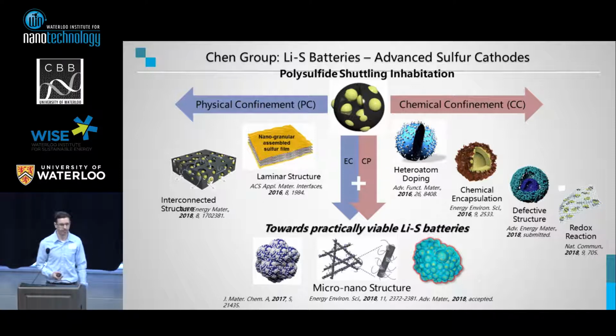But there are similar life cycle considerations for that as well. So right now, this technology is only very early beginning to be introduced into the market, and there's still much more improvements to be made. So the main consideration here in terms of chemistry is that sulfur, when it joins with lithium ions, it can produce soluble components, which will then leach into the electrolyte and cannot be recovered. And so a lot of the nanotechnology solutions are finding how to confine that sulfur or those sulfur components in order to keep it at the electrode location, so that it will not lose its capacity over a number of cycles.